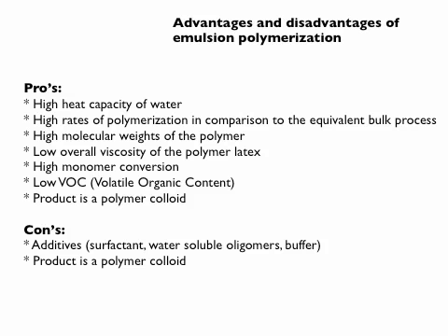Next, a high rate of polymerization in comparison to the equivalent bulk process. This is interesting. For example, an emulsion polymerization of styrene typically takes between 3 and 4 hours, depending a little on conditions, but the equivalent bulk polymerization takes way over 24 hours. That's good. It's way faster. Why is it faster? We'll come back to that later. Another thing, we can make very high molecular weights. With bulk polymerization of styrene, roughly 150,000, it really can't go much higher. Emulsion polymerization, 1 million, not a problem. Higher molecular weights could mean more mechanically robust materials, so that could be interesting. And obviously, if you want lower molecular weight, you just add a chain transfer agent and you can make the low stuff. So that's good.